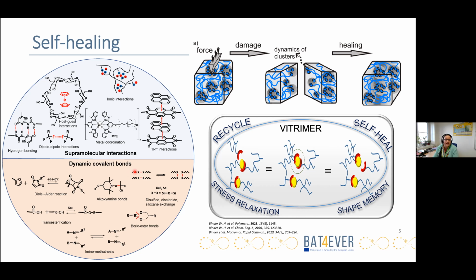Intrinsic self-healing is an autonomous self-healing process, so we don't need an external stimulus, and it depends on the tailoring of the dynamic bonding interaction at the molecular level, or on an interplay between the diffusion and entanglement of polymer chains. In general, there are two possibilities to introduce self-healing functionality into polymeric materials, either via so-called supramolecular interactions or